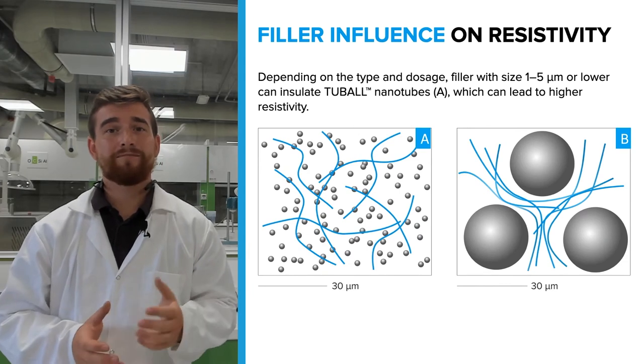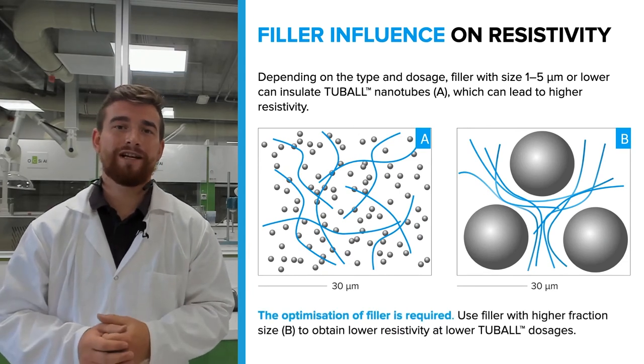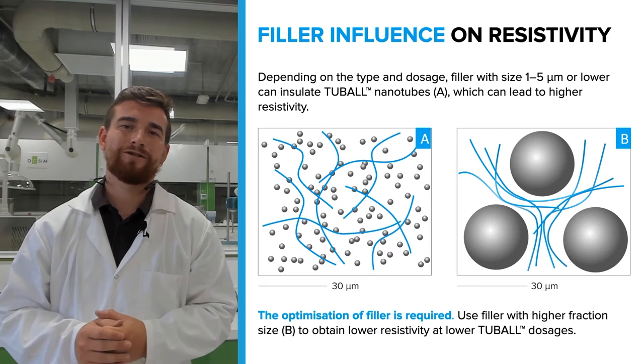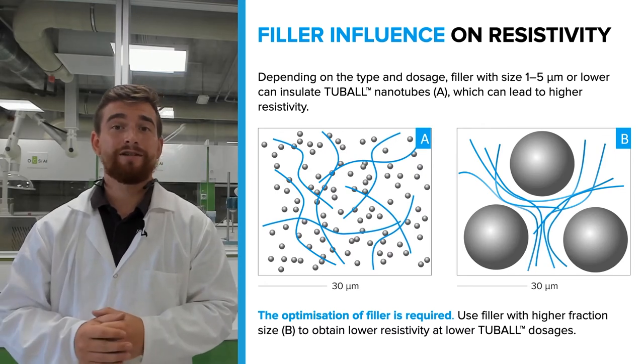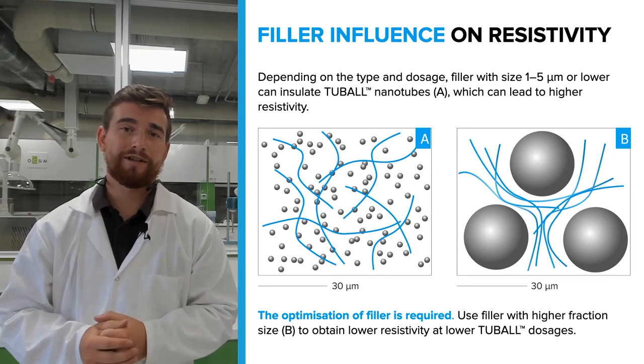Our internal research shows that fillers with mesh sizes between one to five microns or less can insulate the TUBALL nanotubes, which then results in a decrease of your conductive properties. So we recommend using fillers with larger particle sizes to make sure that you get the lowest resistivity level at the lowest Tubal Matrix dosage.